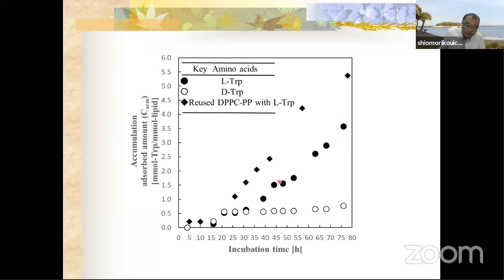After the first adsorption of amino acid on the particle containing DPPC, the second adsorption is a little bit faster than the first adsorption like this. But on the other hand, D-type tryptophan did not adsorb on the particle even after long time contact.